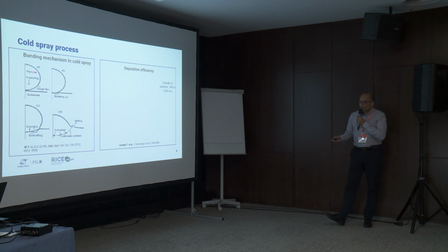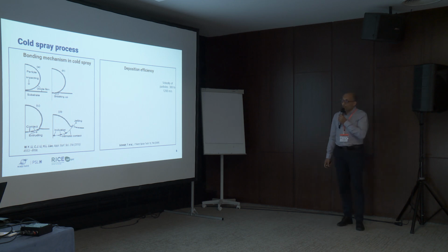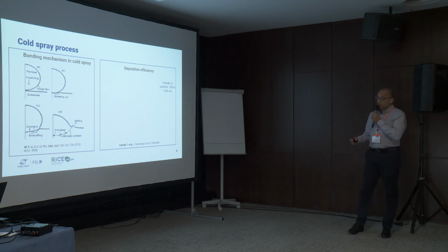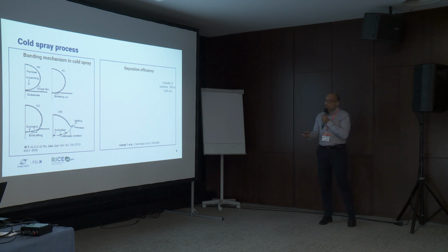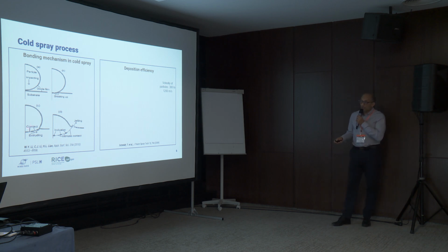Here you can see the bonding mechanism in the cold spray. You have four main steps to understand what is happening when you have an impact of the particles at high velocity. The first step is the impact, and after you have the breaking up of the oxide layers from the particles and the substrate. Then you have the contact of the oxide-free surfaces and an extrusion, and in the final step, high deformation and high shearing, leading to the bonding.